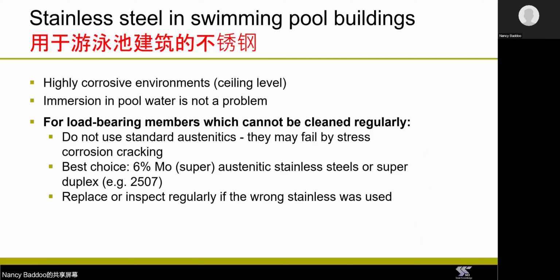Finally, I have to tell you that caution needs to be exercised when stainless steel members containing high residual stresses, say due to cold working, are used in chloride-rich environments, particularly indoor swimming pools, and particularly at the ceiling level where contaminants tend to accumulate. And you need to watch out for components such as highly loaded cables, as they may be susceptible to stress corrosion cracking.